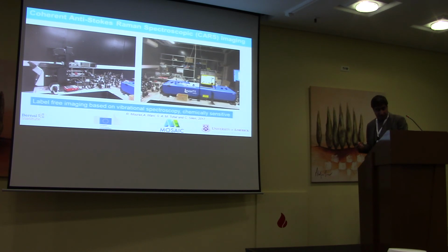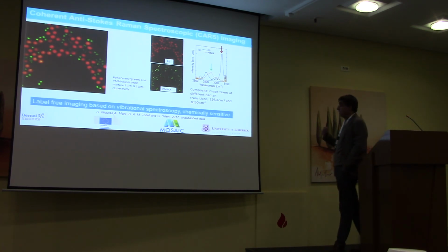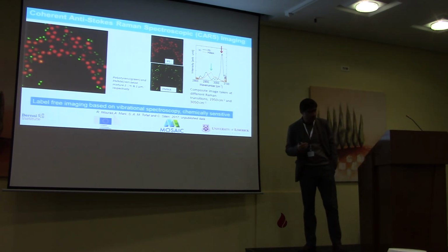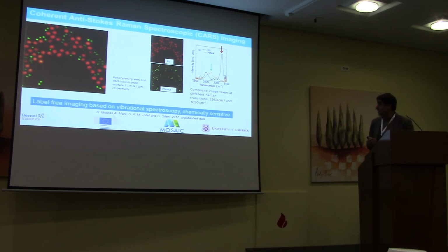For example, the left-hand image is a coupled image of polystyrene and PMMA, where the image was recorded at 2 different wavelengths using the absorption bands of these 2 materials, and here you have a separate image. This is again a label-free technique which can give us a 3-dimensional map of the surface, with a tunable laser between 1 to 20 micron.